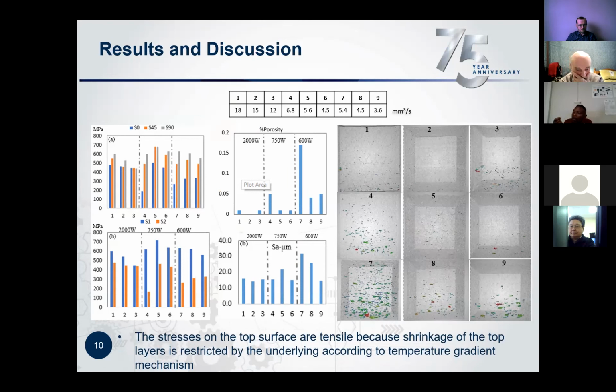The stresses on the top surface are tensile because shrinkage of the top layers is restricted by the underlying material, and this is clearly described by the temperature gradient mechanism. I've tried to explain that previously in my background and motivation.